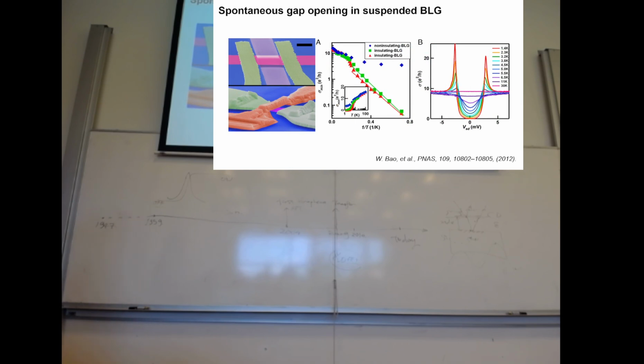And also people did some very sophisticated experiments of suspending graphene into this kind of structure. So what they did is that they have a bilayer graphene suspended in vacuum, and then they managed to make a bridge on top, which serves as a top gate, and there's a bottom gate, of course, which is silicon doped. So this is a very complicated structure. You have to use very careful experimental tools, for example, to dry this graphene from the solvent phase. You have to use a critical point dryer, which is very complicated.